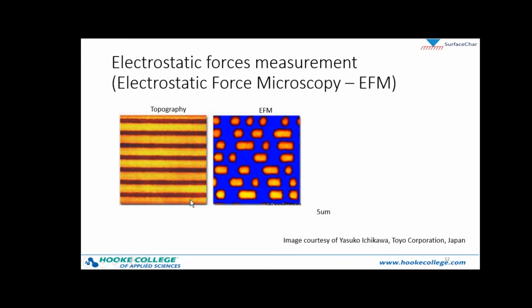The final electrical method I will survey is electrostatic force microscopy, or EFM. This method maps the effect of long-range electrostatic force gradients on an oscillating cantilever and is useful for applications such as electrical failure analysis, measuring charge distribution, and detection of trapped charge. It's convenient primarily to image qualitative electrical properties, as the electrostatic force is measured between a biased cantilever and the surface as the lever is lifted a prescribed amount over the surface. This is that two-pass mode that I had mentioned in the beginning.